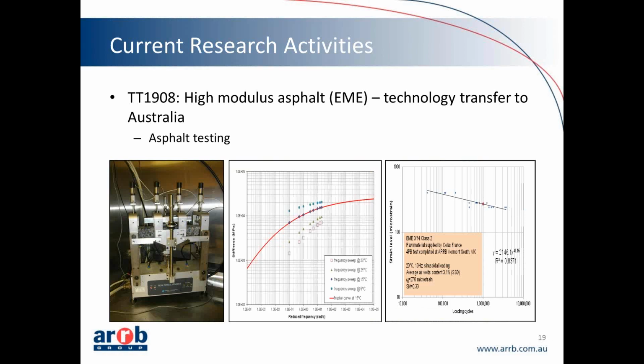So one of the other aspects of the testing that we did was we took the standard asphalt beam fatigue testing that we do quite often in Australia, where the Australian method is one strain level, one temperature, 3 asphalt beams. The Europeans do things a little bit differently. The first thing that they do is they take 6 to 8 asphalt beams and compact them, and once they're compacted, we test those at 4 different temperatures, and we run a frequency sweep at about 9 different frequencies, and from that we can develop a master curve. So that's what you're seeing there in the first picture.